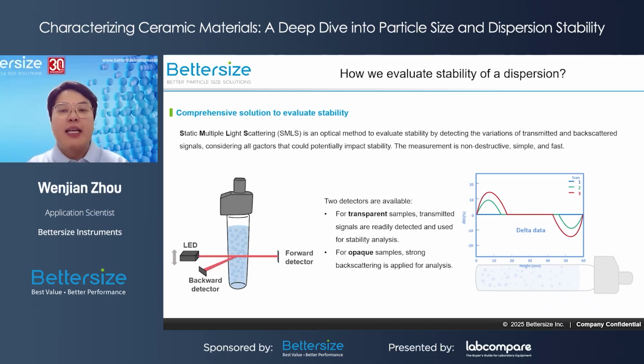A setup that contains an LED, a forward detector, and a backward detector moves vertically along the sample cell to capture the transmit and the backscatter signal every 20 micrometers. For transparent samples, we use the forward detector to capture the transmit signal. If the sample is opaque, we use the backward detector, since in this case, transmission is almost blocked. Let's take sedimentation as an example.